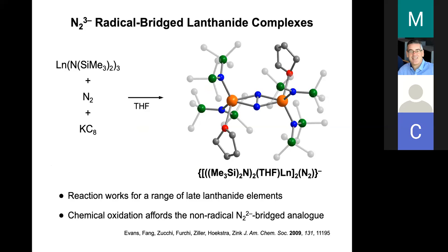And that's hard to do because, as we said, the f electrons of the lanthanides are buried within the core electron density and don't like to engage with other orbitals, with ligand orbitals. And so lanthanide ions usually show extremely weak super exchange interactions. Remember, super exchange means that the spin of the metal can interact with the spin of another metal by propagating through intervening non-magnetic atoms and orbitals.